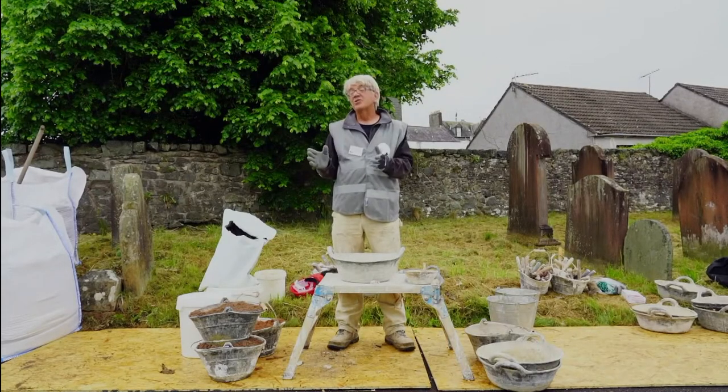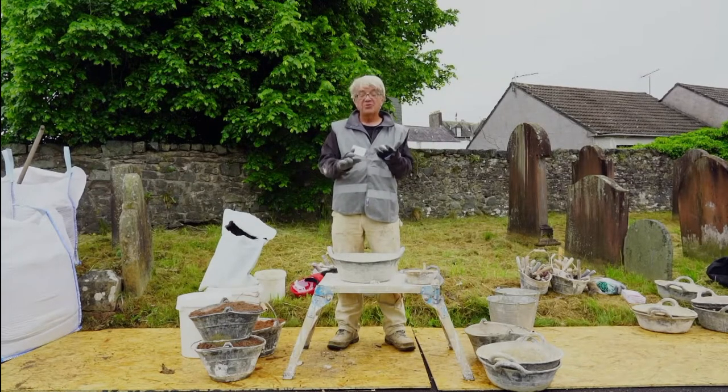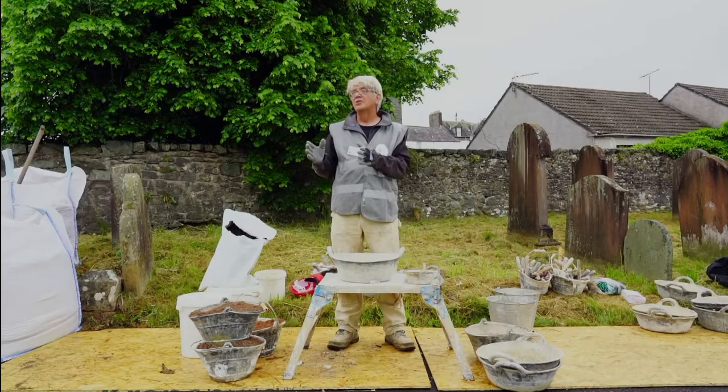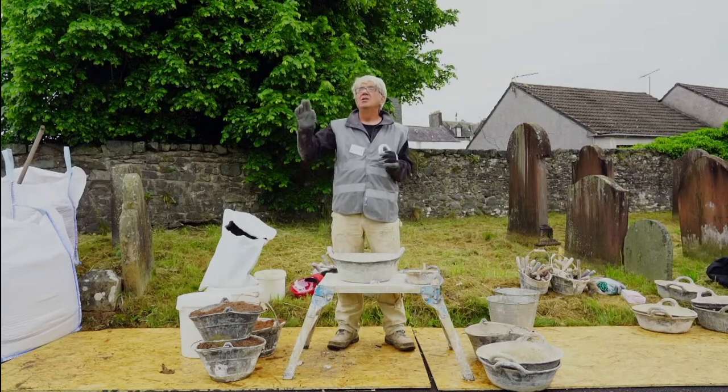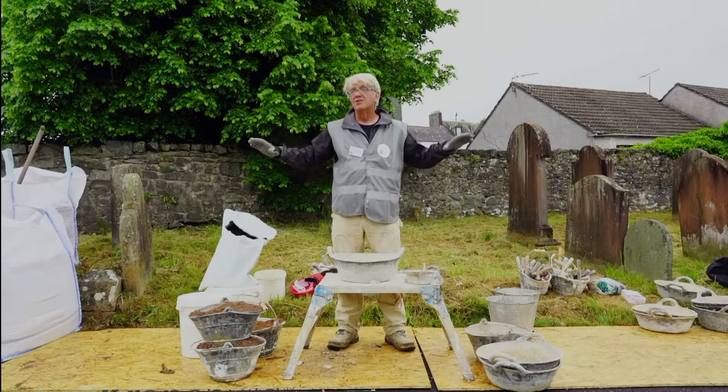I will touch just very briefly on cement lime mortars. They were a compromise when they were originated in the early 20th century. You might put 1 cement, 3 lime, 12 sand. That was a basic mix. You might put 1 cement, 2 lime, 9 sand. Or you might do 1-1-6. 1-1-6 was a mortar that, until John Ashurst said otherwise, was reserved largely for the tops of chimneys and really exposed situations. Before we embraced NHL, it had come to be seen, it still is in America, as somehow a conservation mix. It really is not.